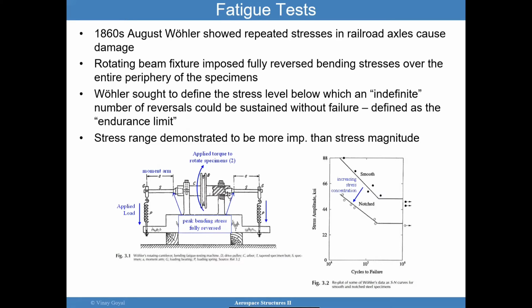In the 1860s, Wöhler showed repeated stresses in railroad axles causing damage. So as a consequence, the rotating beam test was a good solution to this problem. It imposed fully reversed bending stresses over the entire periphery of the specimen. And the point I want to make here is that Wöhler sought to define a stress level. He was trying to figure out what stress level will give me infinite life. That's what he was looking for. If I apply stress amplitudes, is there a stress where I can get infinite life? Is there a way I can keep going forever? And he defined that as the endurance limit.